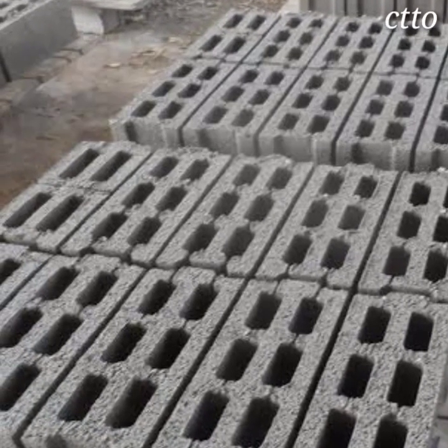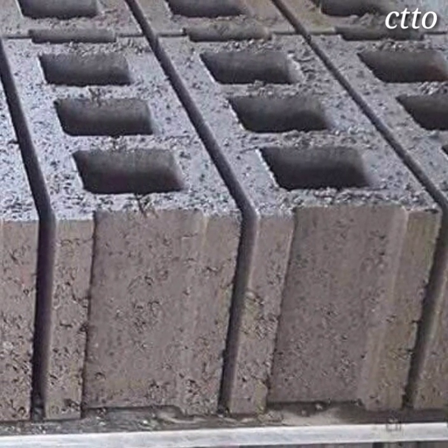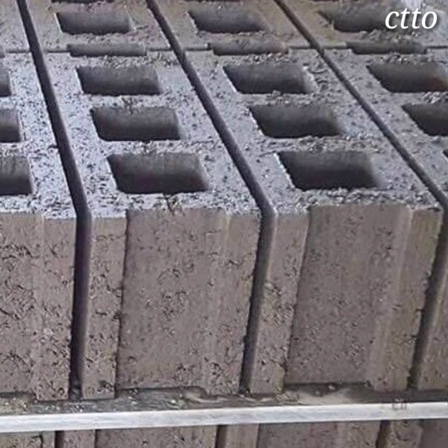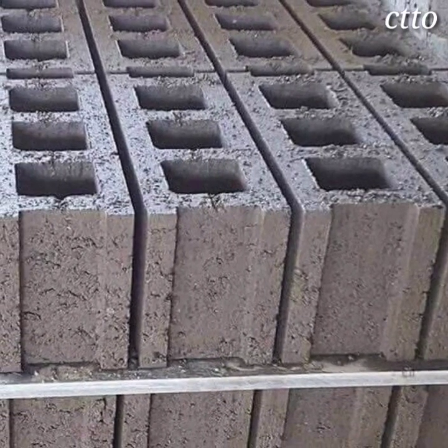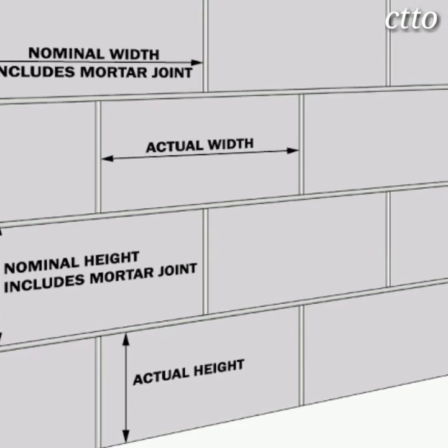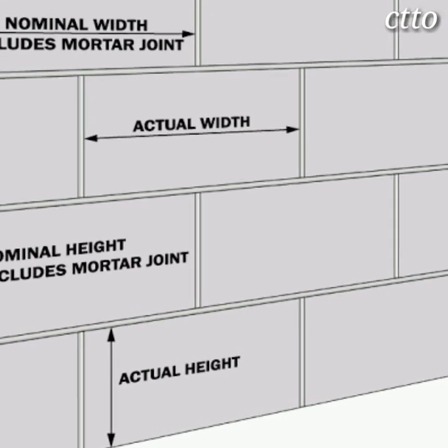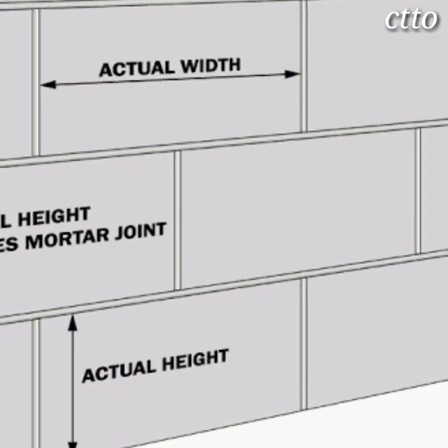The delivered units shall be inspected and should be sound and free of cracks and other defects. For strength, moisture, and absorption determination, 6 units shall be selected from each lot of 10,000 units or fraction thereof and 12 units from each lot of more than 10,000 units.